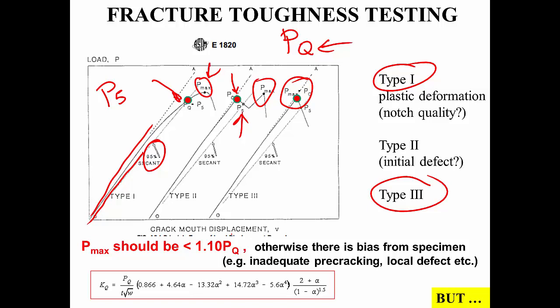maximum. So if the second peak is higher, then there is a problem, and there must be something like a bias from the specimen, either inadequate pre-cracking or some local defect that gave away, excuse me, at the first peak. So essentially you need to repeat the test if the difference between P maximum and the first peak is more than 10%.